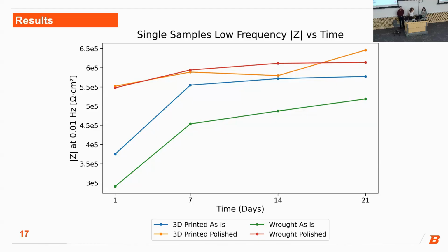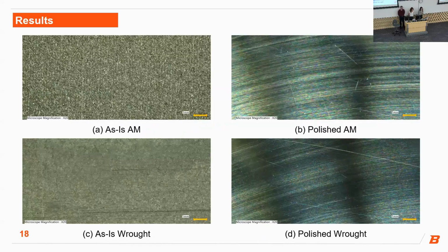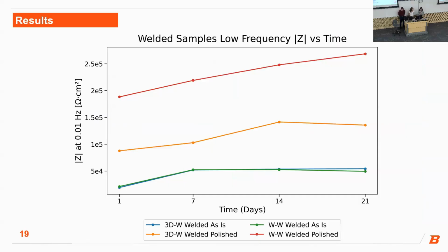Our polished samples also consistently maintained higher impedance values, indicating a more stable and protective passive film. We think this is likely due to fewer surface defects, uniform oxide growth, and reduced corrosion initiation sites. Here are some images taken of our single samples on the Keyence microscope after the 21 days in the sodium chloride solution. As you can see, there is no visible corrosion, and this does reflect what we saw in our EIS data.